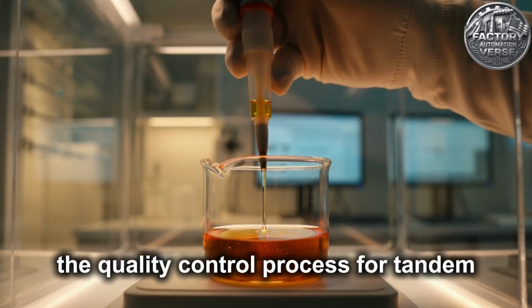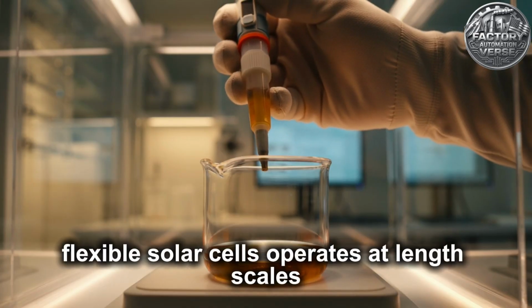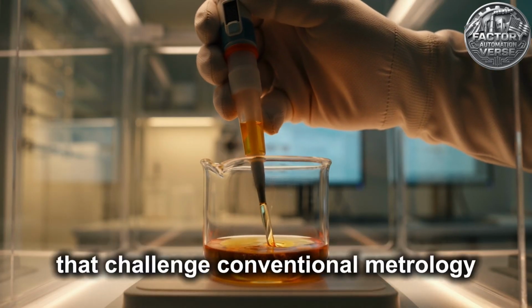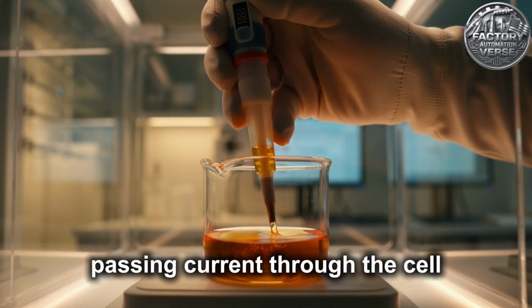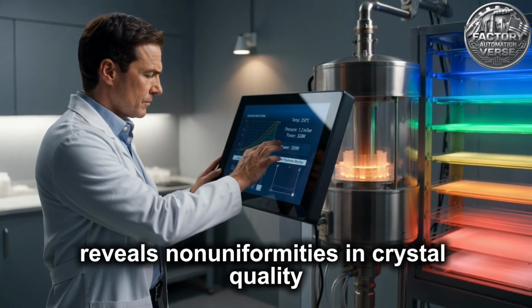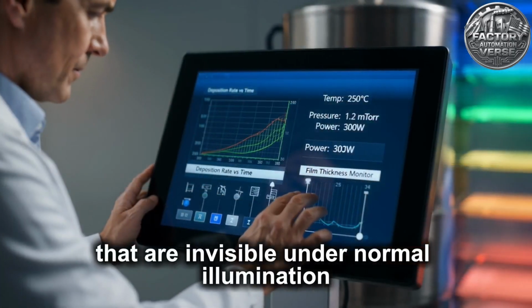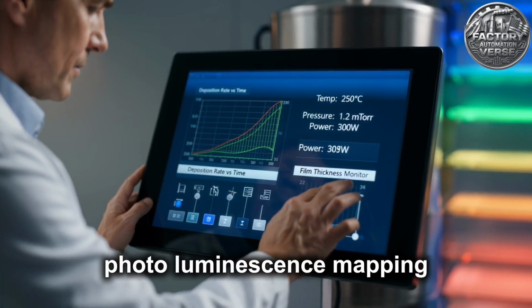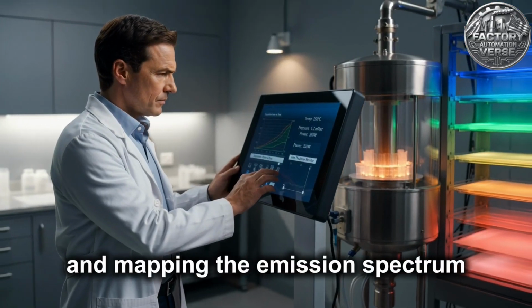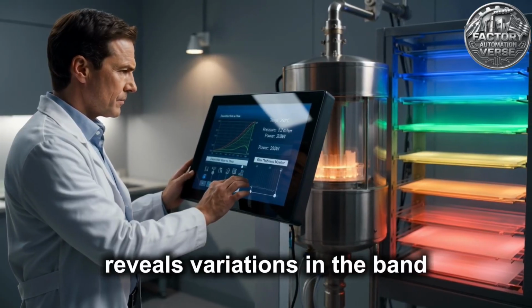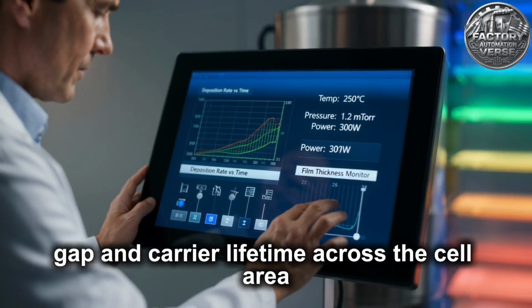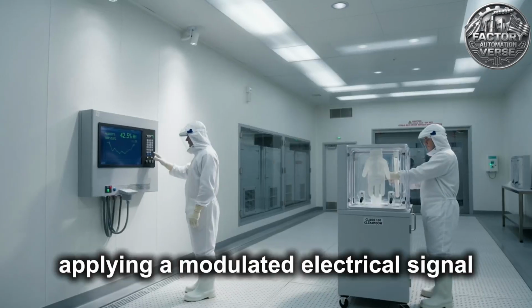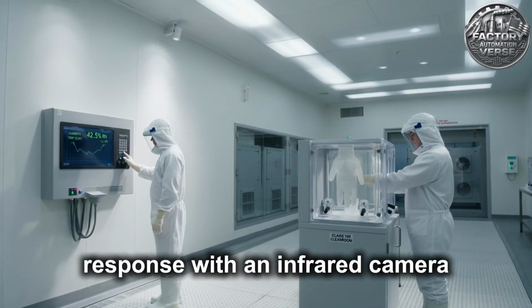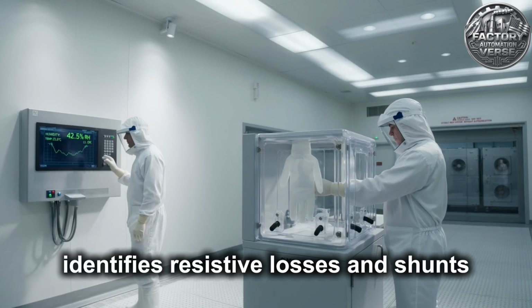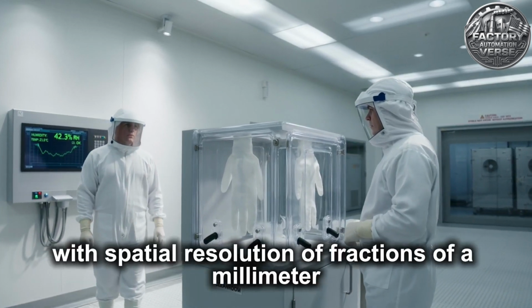The quality control process for tandem flexible solar cells operates at length scales that challenge conventional metrology. Electroluminescence imaging, passing current through the cell and imaging the light emitted, reveals non-uniformities in crystal quality and defect concentrations that are invisible under normal illumination. Photoluminescence mapping, illuminating the cell with a laser and mapping the emission spectrum, reveals variations in the band gap and carrier lifetime across the cell area. Lock-in thermography, applying a modulated electrical signal and mapping the thermal response with an infrared camera, identifies resistive losses and shunts with spatial resolution of fractions of a millimeter.